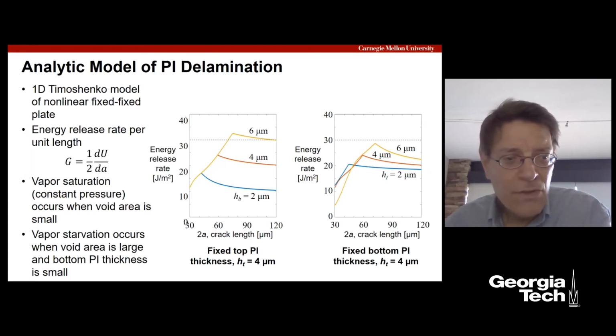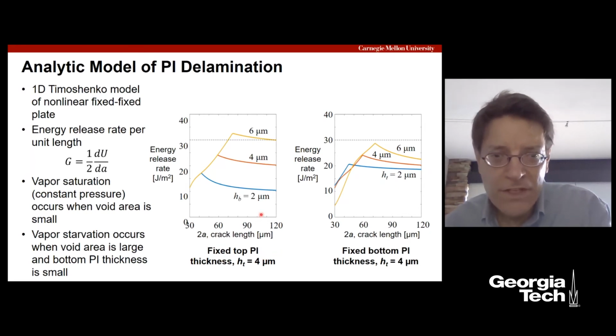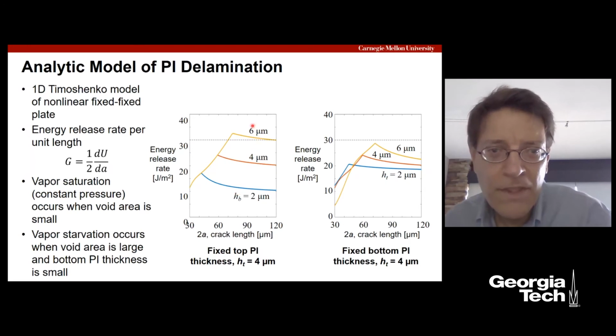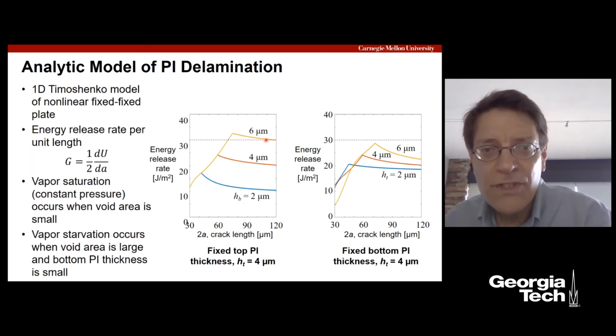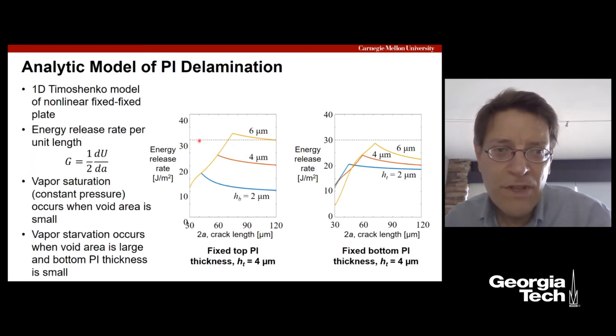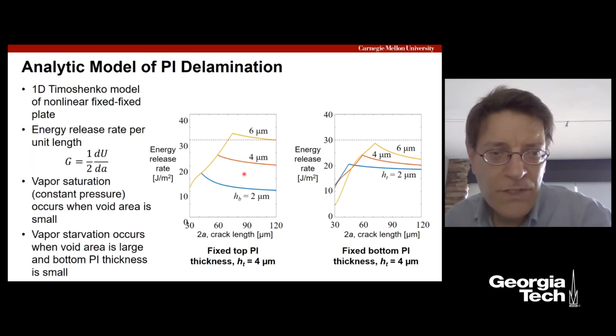And what we found with this model is that we're plotting crack length versus energy release rate in both of these two plots. The one on the left has a fixed top polyimide thickness, so we're varying the bottom polyimide from 2 to 6 micron. And notice as the bottom polyimide thickness gets thicker, the energy release rate goes up. And that's a bad thing, because when you get above a certain limit, in this case shown by this dotted line, we have the problem of delamination. So bottom thickness matters a lot.